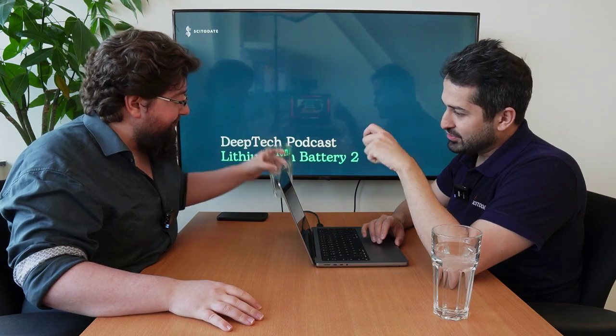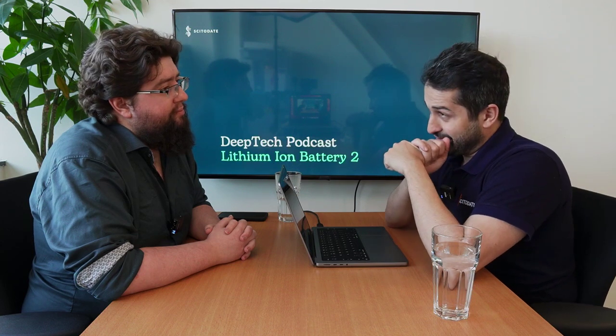So as you charge and discharge, this gets thicker and thicker, right? Because there is some residual electron that moves, and there is some resistivity, and then there is growing, right? So the other one is called lithium plating. We were talking about it on the graphite. It might be that instead of ions going inside the graphite between the layers and getting their electron back, they might get it on the surface of graphite.